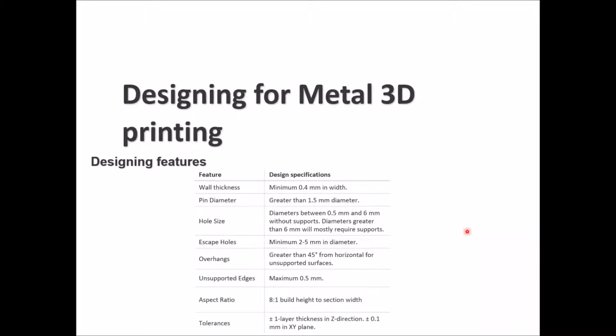For the design features, a quick overview: wall thickness should be minimum 0.4 millimeters in width. Pin diameter should be higher than 1.5 millimeters in diameter. Hole size: diameter between 0.5 to 6 millimeters without support. Diameter greater than 6 millimeters needs support. Escape holes need to be minimum 2 to 5 millimeters in diameter. Overhang should be greater than 45 degrees from horizontal to keep it unsupported. If you have unsupported edges, then the maximum is 0.5 millimeters. Aspect ratio 8 to 1 build height to section width. Tolerances should be plus or minus 1 layer thickness in Z direction and plus or minus 0.1 millimeter in the XY plane.